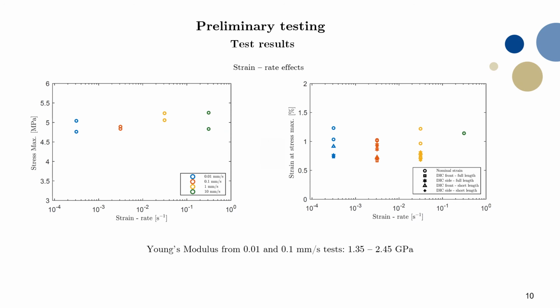About the strain rate effects, there was no strain rate effect neither on the strength, so on the maximum stress, nor on the strain at maximum stress. The Young's modulus was also calculated from the low strain rate testing, so from the 0.01 and 0.1 millimeter per second tests, and the values calculated were in accordance with values from literature.